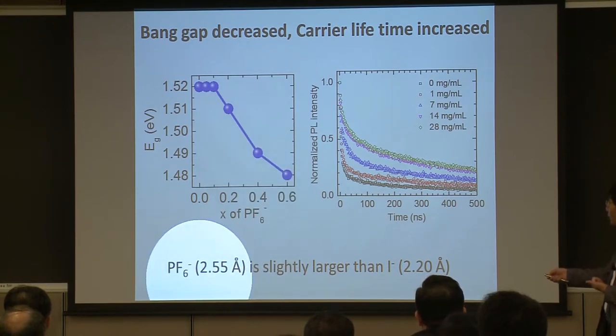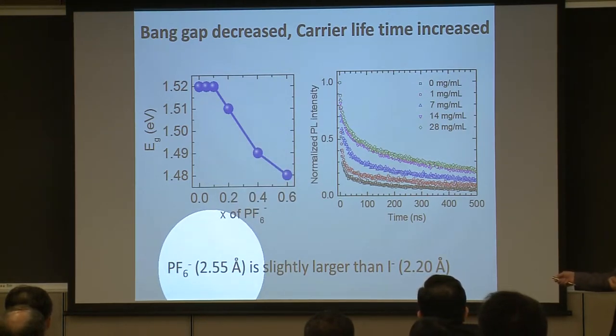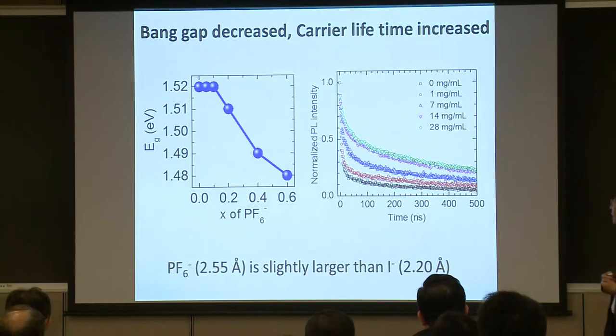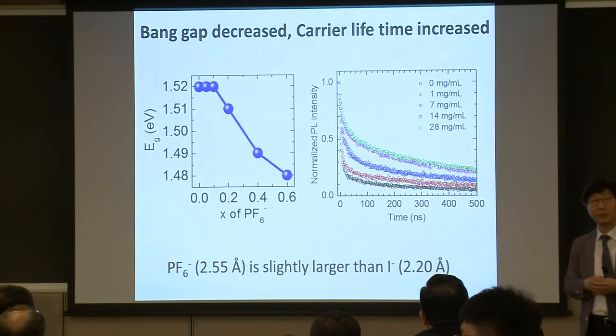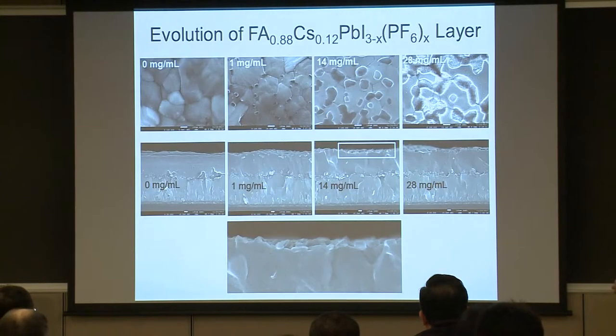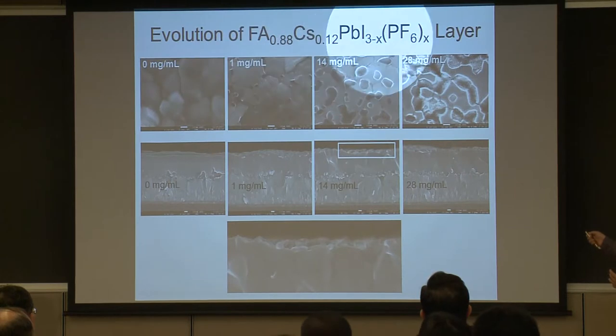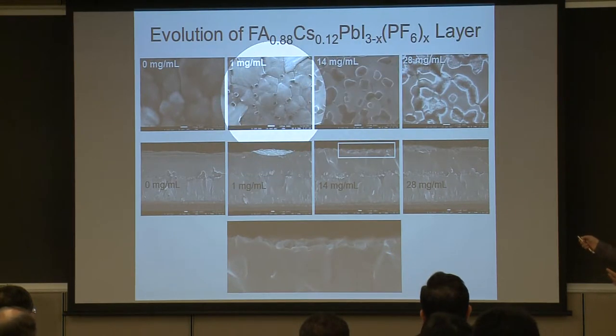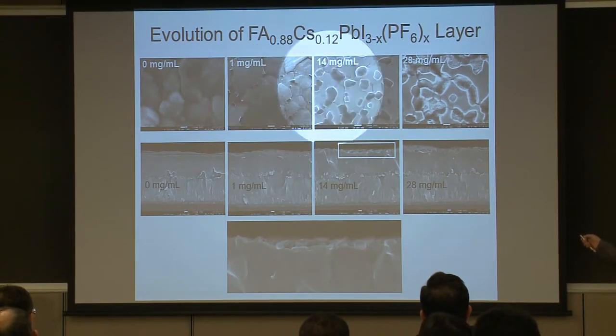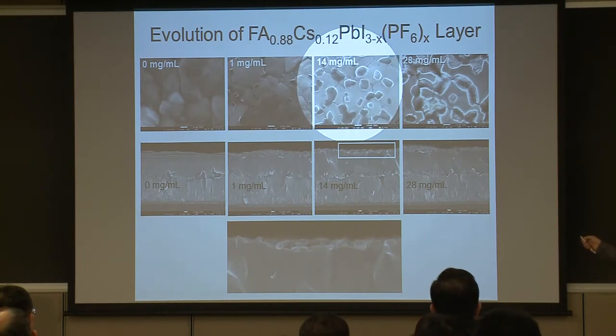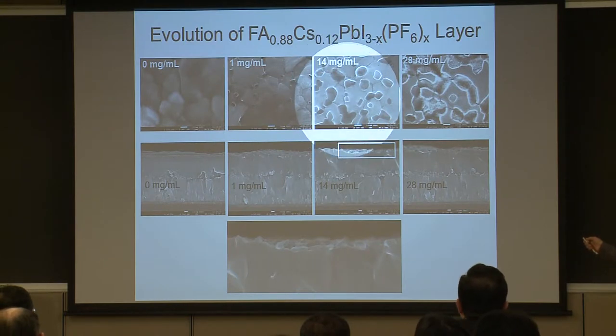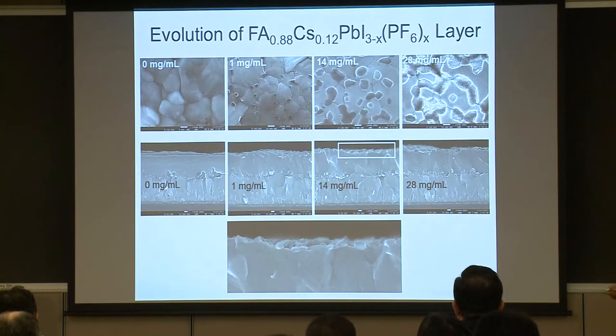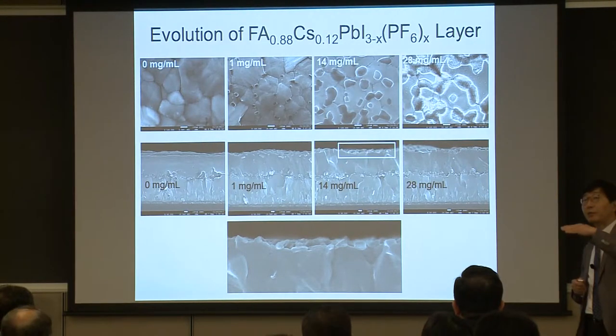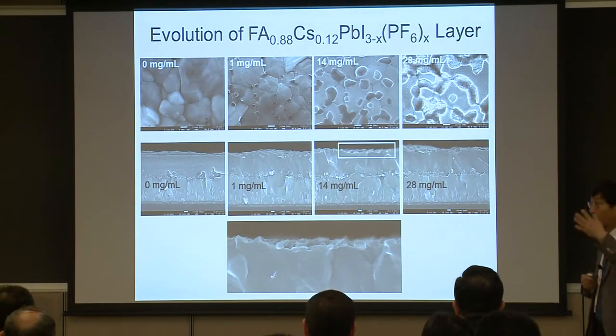This is probably because the PF6 ion size is slightly larger than the iodide, and also we found that the carrier lifetime increases by this ion exchange reaction. Interestingly, when you spin coat with the FA PF6, you can see some second phase. And if you increase the concentration, the second phase grains gradually increase. And this second phase is formed on the surface of the perovskite. This is called the layer-by-layer structure, not the surface modification.